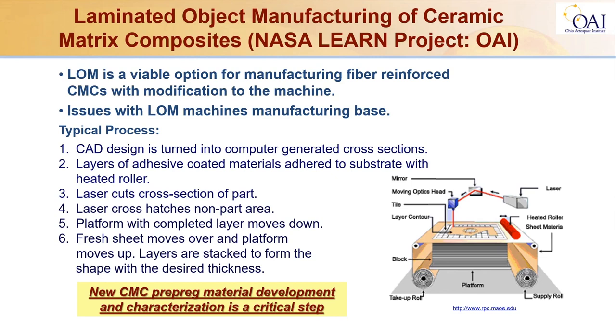But the process itself is like they're listed here. You basically have a CAD design. You can make the part and design it and then turn it into computer generated cross sections. Then you basically have these preforms or adhesive coated materials. They pass through a heated roller, a laser cuts the cross sections and laser cross hatches in the non-part areas, and then the platform moves down, and the fresh sheet moves over the platform. And then you keep on stacking the layers to make the desired shapes.